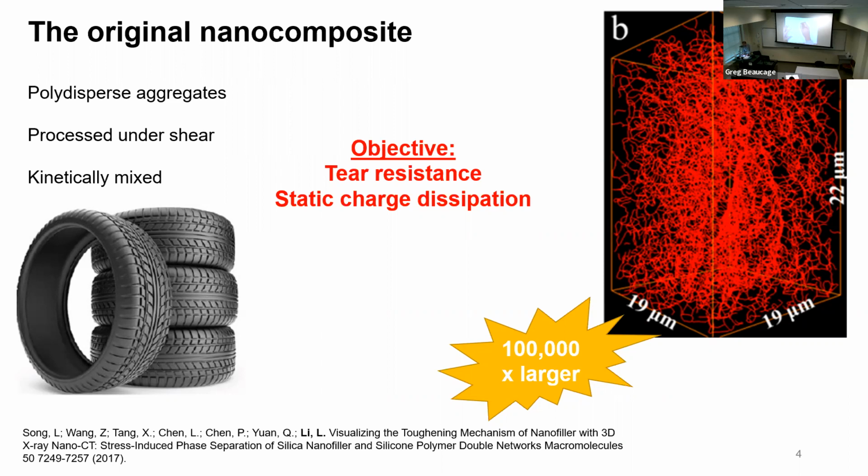So there's like level 1, level 2 is that. Then those things cluster together to make level 3, and then those things make that network that you see. This thing is something like 0.1 micron maybe, and then this thing gets to like 2 micron, and this is hundreds of microns. Right, so you start out nanometer all the way to micron. You have like 1, 2, 3, 4 levels of the thing. It's complicated. It's not so simple.